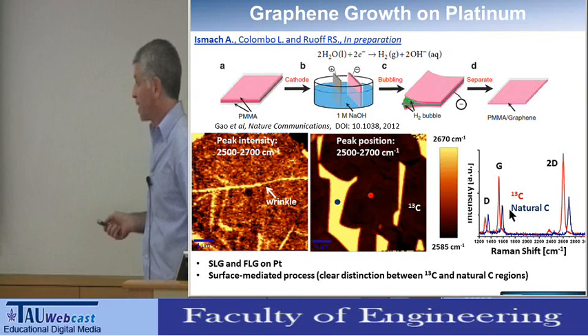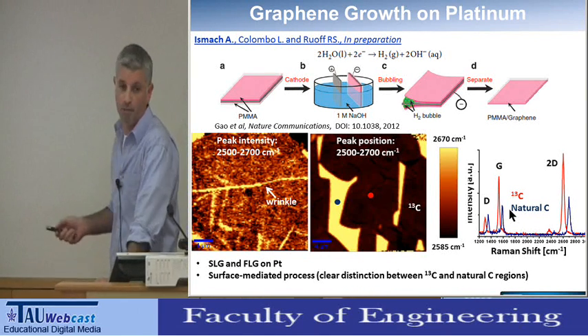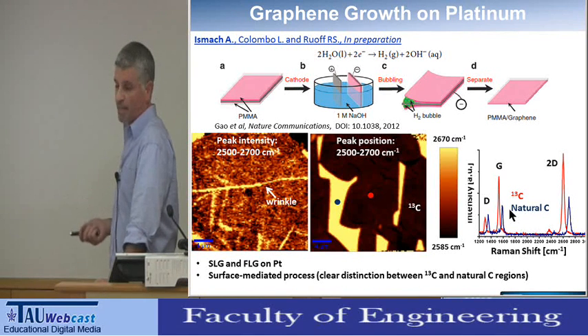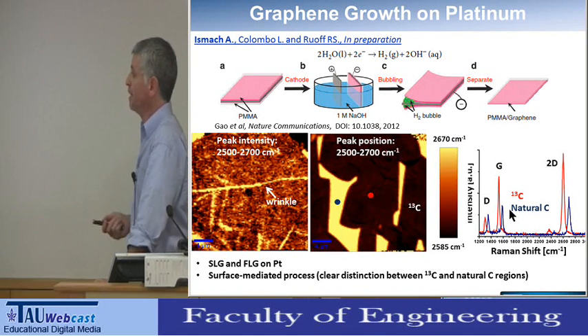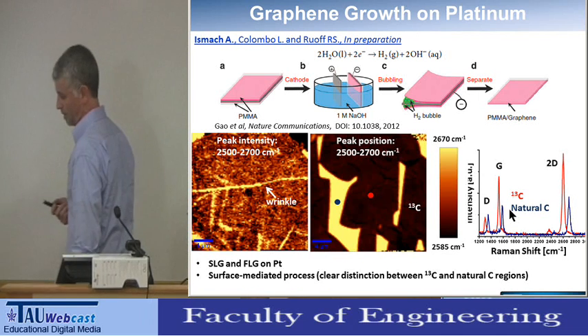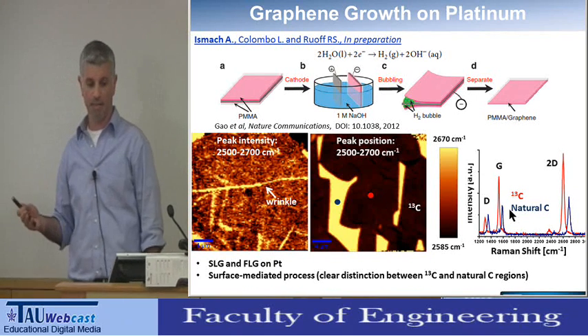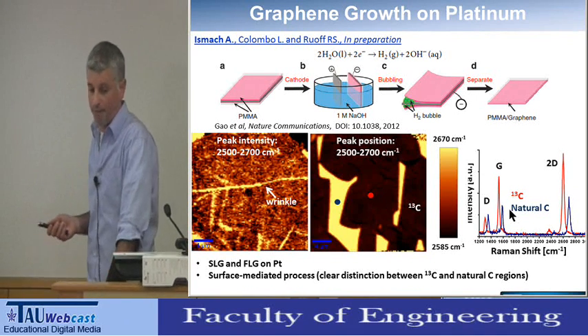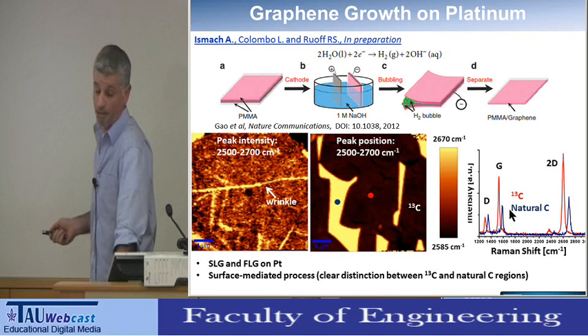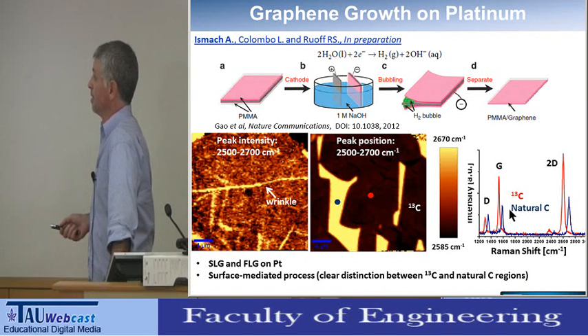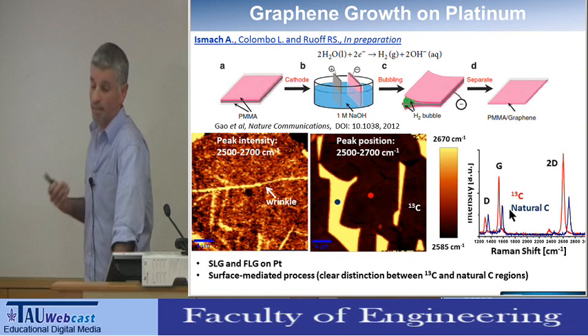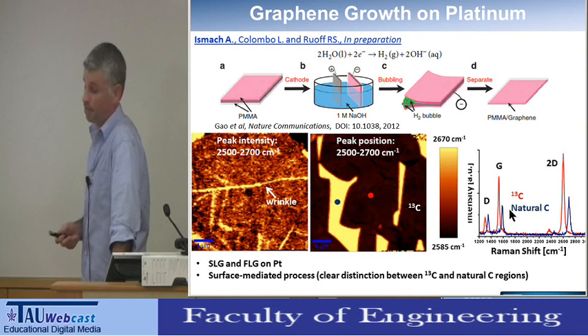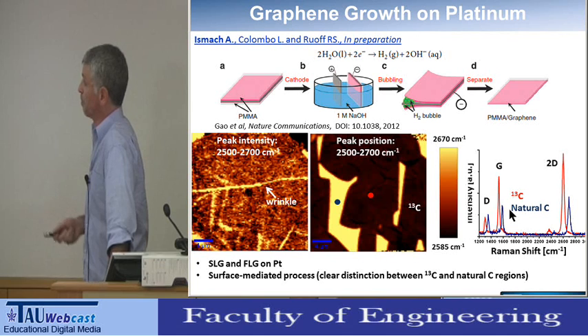But we can also get few layers of graphene on the platinum. So it's obvious that the solubility explanation can't explain the growth of single layer graphene on platinum, because it is a thermodynamic parameter, and the kinetic parameters are important as well.